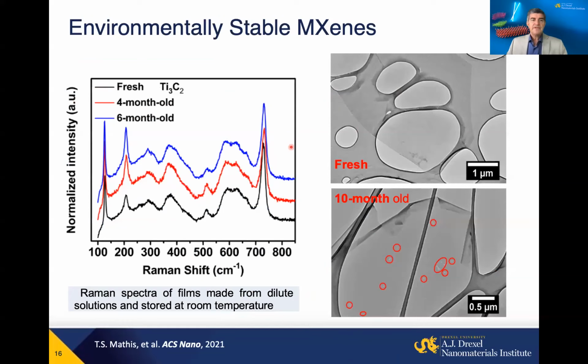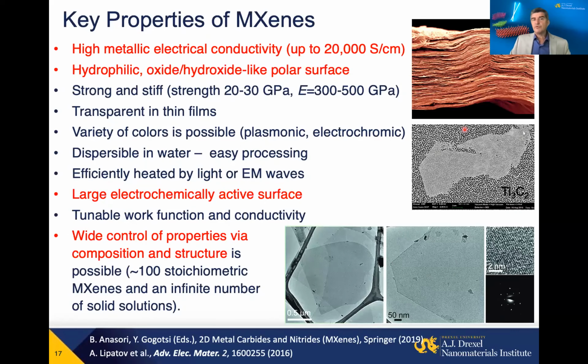One more thing: initially, we observed degradation of materials, not immediate, but within days or weeks in solution. In the presence of humidity and water, the flakes would degrade. When they're produced in a film, they're stable for a very long time, at least years. But when you have monolayer flakes in solution, they will degrade. We were able to resolve this issue. We published a paper a couple of months ago in ACS Nano showing that if we get stoichiometric MXene with no vacancies in the carbon sublattice or oxygen present, we can get a material which, after 6 months in colloidal solution at room temperature in an argon-closed vial, will not change at all. Even after 10 months, we can see only a couple of pinholes appearing after storage. They are circled here because you would not even notice them otherwise. So they're stable for processing, storage, and shipment before you produce the films.